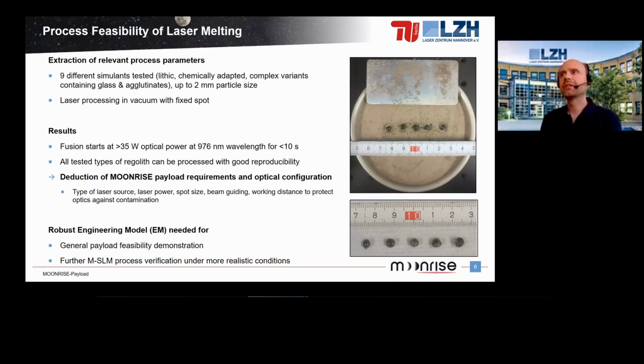Then the next step was testing the process feasibility of laser melting. We used 9 different simulants, so lithic, chemically adapted, and also physically adapted simulants with particle sizes up to 2 millimeters, and we processed them in vacuum with a fixed spot to achieve these 0D pearls, which are seen on the right. The fusion starts in our configuration at 35 watts of optical power at a wavelength of 976 nanometers, and you only need less than 10 seconds to melt the regolith simulant. All the different types of regolith simulant we had could be processed